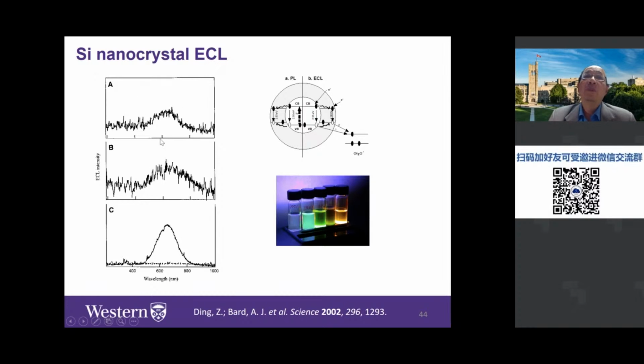Then we do the electrochemiluminescence with the silicon nanocrystal. And in fact, you can see that the wavelength is way redshifted. Okay? So then we developed this kind of schematic. That means if you excite these silicon nanocrystals with light, that means you generate photoluminescence, then it's blue. But if you excite these nanocrystals with electricity, then you get this kind of red light emission.